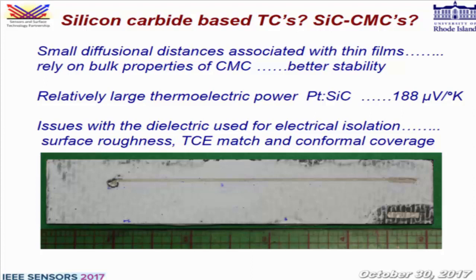The material itself, from the picture before, you could see it has a very rough surface, so that makes it hard to employ thin films on it. And for the dielectrics that we use, shown here, this is mullite. It's very hard to pick an appropriate dielectric because of thermal expansion coefficient mismatches between the dielectric and the CMC material. So you have to use the correct dielectric.